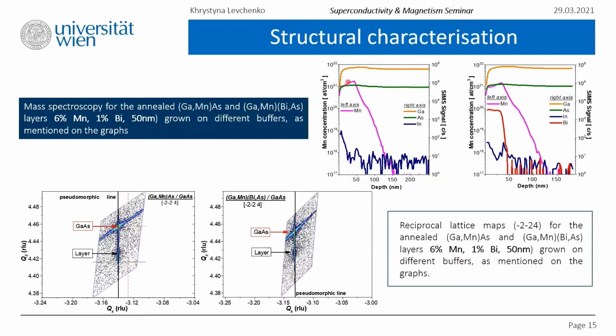So you may see that manganese is present only for the first 50 nanometers. After that, the signal drops down. And for the quaternary compounds, the signal from bismuth also drops around 50 nanometers. The relatively low decline angle in the manganese dopant curve is connected with the interlayer out-diffusion of atoms, mostly into the buffer underneath. It happened during the growth procedure. Another dropout in the signal visible for the first few nanometers, let us say specifically for manganese, is understood as a result of the post-growth annealing treatment, which resulted in more active atom out-diffusion to the surface in the shallow layers in comparison to those sitting deeper.